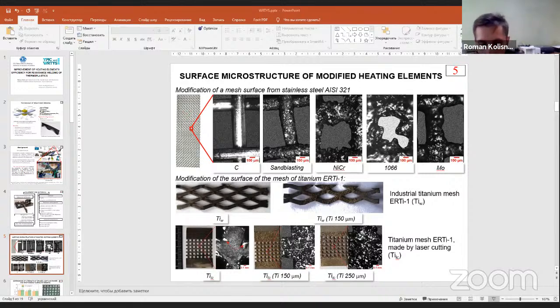So we got a result of increasing welding strength by 13%, but it did not satisfy our demand. So we switched our heating elements to heating elements based on electroconductive polymer composites made of high density polyethylene and filled with carbon black, which is electroconductive. In this case, as you can see on the slide, during electrothermal measurements, the best results we got were on composites filled with carbon black, since composites filled with carbon fiber and combined filler carbon fiber and carbon black showed decreased temperature when we applied a certain voltage.